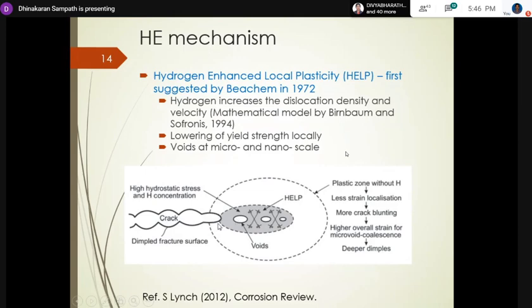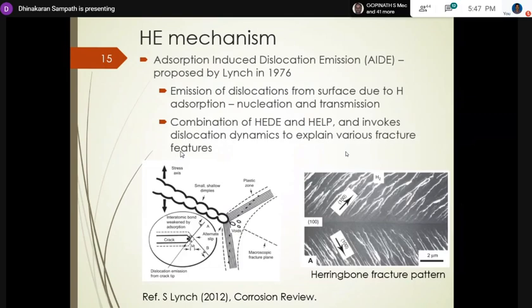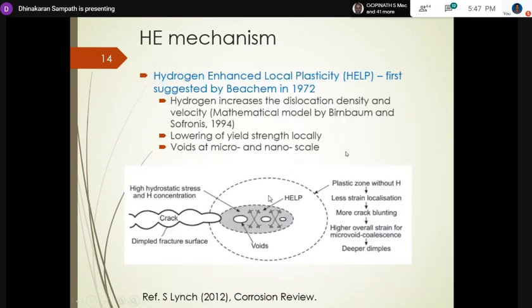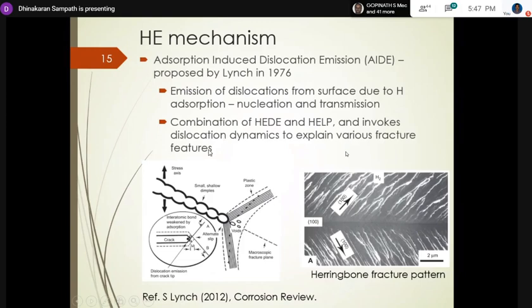See, in the presence of a crack, we normally have a big plastic zone because of very high stress, and once the material reaches the yield point, it creates a plastic zone. In the presence of hydrogen, that zone is very small, and inside it we still create voids at the intersections of line defects, that is, dislocations. Even though they appear like a flat surface, at micro and nano scale they have voids similar to what we see in air. So that's actually the very popular model to describe most of the material behavior.